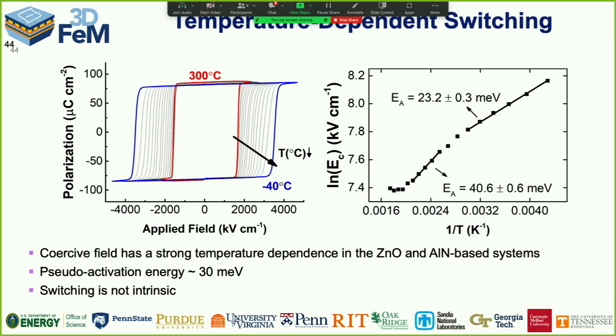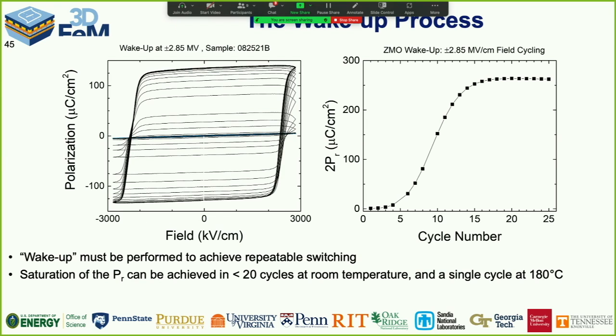The zinc magnesium oxide, as is the case for the aluminum boron nitride, has this hugely strong temperature dependence of the coercive field. Again, we get pseudo-activation energies on the order of 30 millielectron volts. That says it's switching by this domain wall flavored mechanism. We also get wake up in this material.